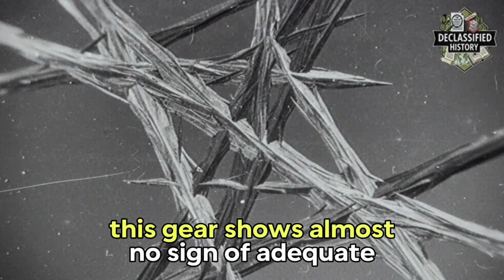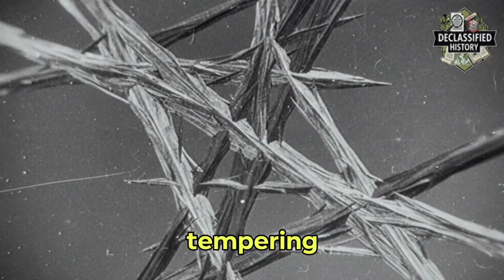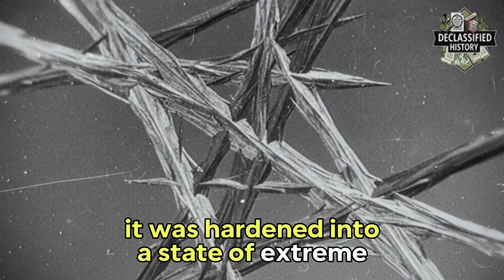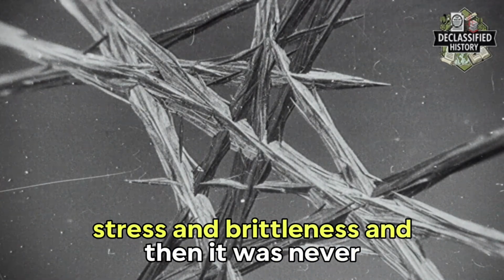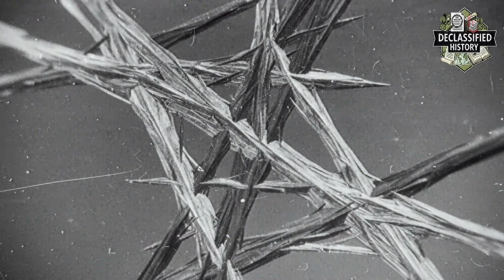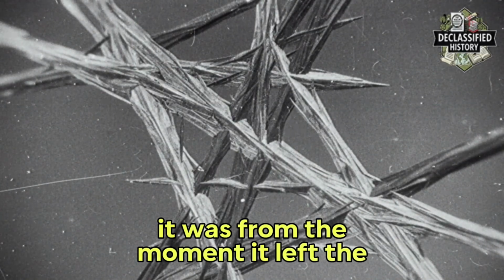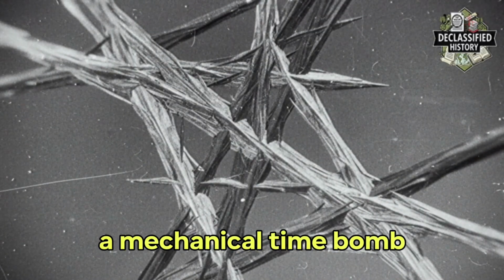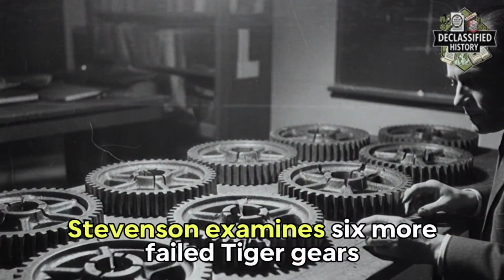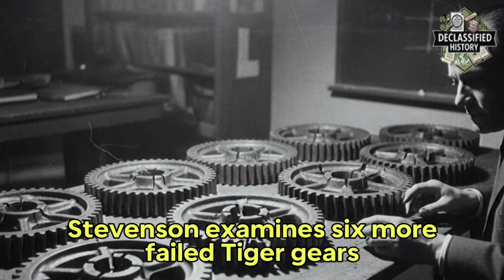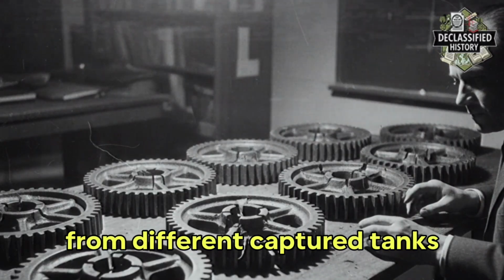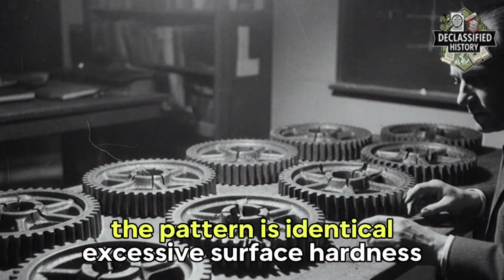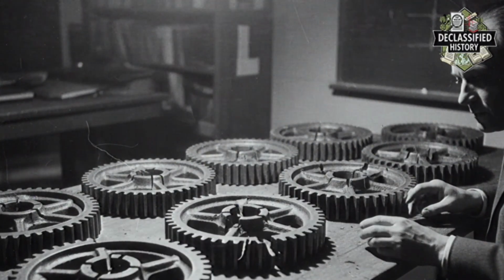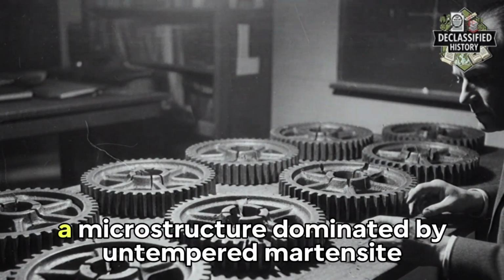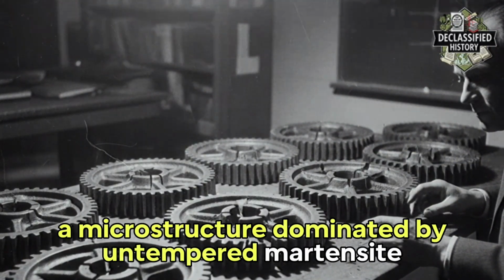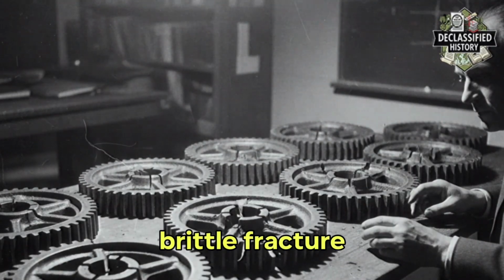This gear shows almost no sign of adequate tempering. It was hardened into a state of extreme stress and brittleness, and then it was never relieved. It was, from the moment it left the factory, a mechanical time bomb. Stevenson examines 6 more failed Tiger gears from different captured tanks. The pattern is identical: excessive surface hardness, excessive case depth, a microstructure dominated by untempered martensite, brittle fracture.